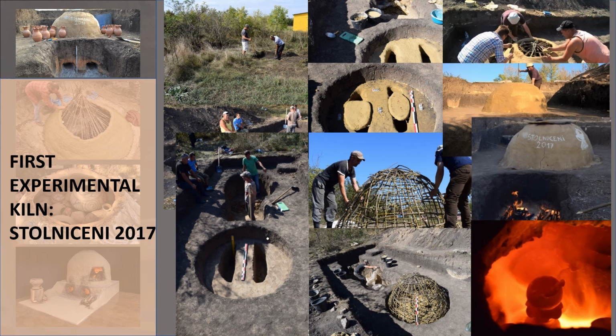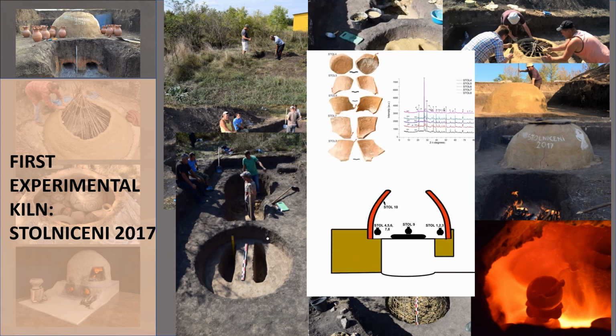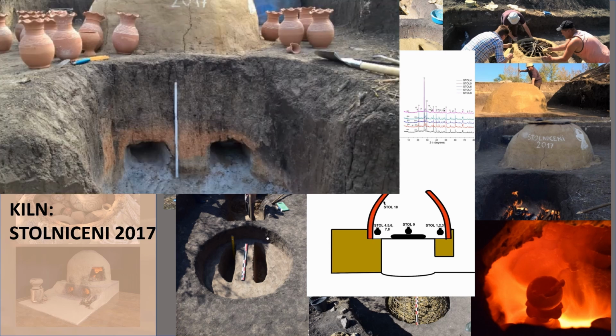Observers noted efficient heat circulation within the kiln, ensuring even exposure of the pottery to the flames. However, while the structure performed well, the maximum temperature reached only around 700 degrees Celsius, lower than anticipated. Laboratory analyses conducted on the fired ceramics, including X-ray diffraction and scanning electron microscopy, confirmed incomplete vitrification, suggesting that adjustments were needed in kiln ventilation and fuel management.